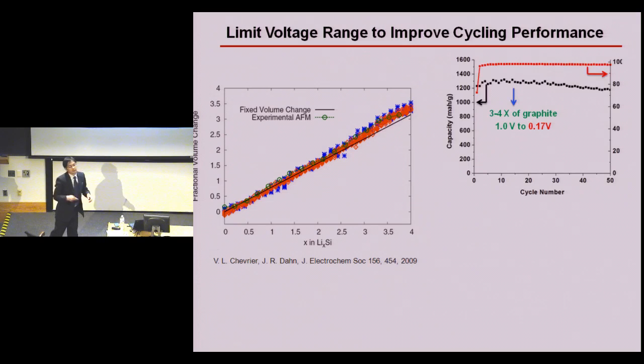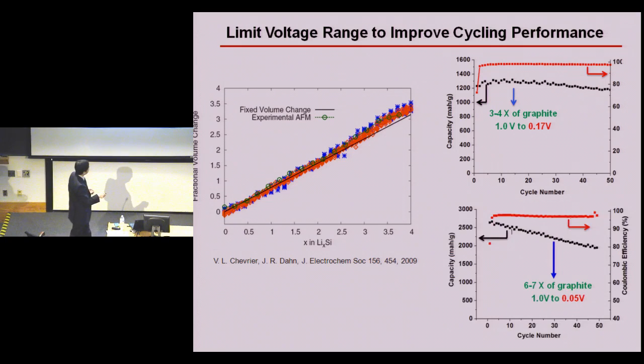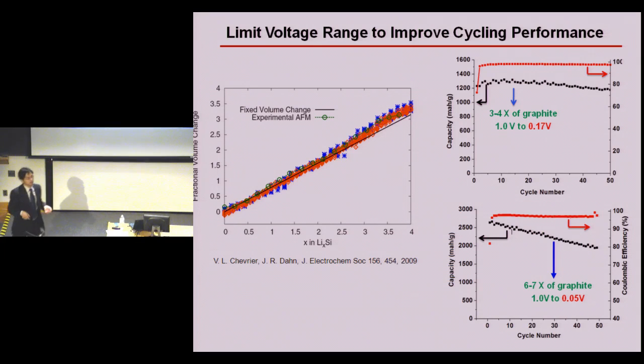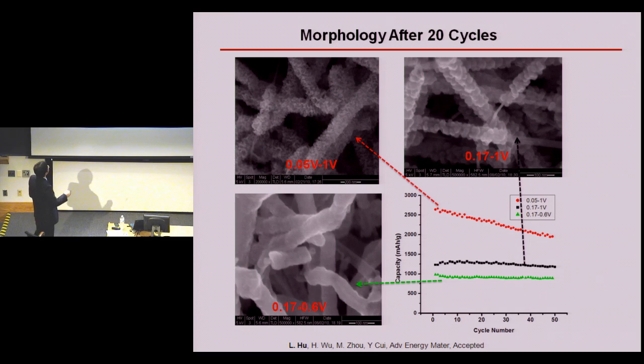We can do this by controlling the cutoff voltage as we charge the battery. So instead of charging down to 0.05 volts, how about we stop as we charge down to 0.17 volts? In this case, we get a capacity of 1,300 milliamp hour per gram. It's smaller compared with the previous case, but the cycling performance is much better. And 1,300 milliamp hour per gram is still much, much higher than the current carbon-based technology. So we see the surface morphology change for these different cutoff voltages, and we see there's a very good correlation between the surface morphology and the cycling performance.